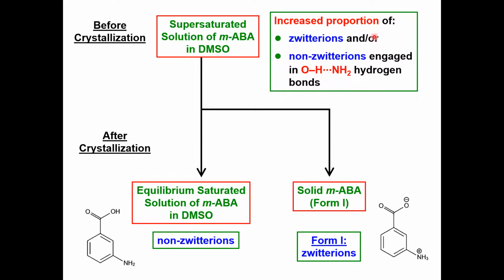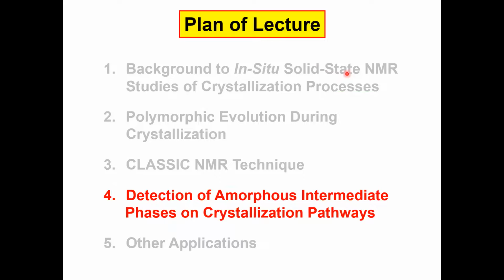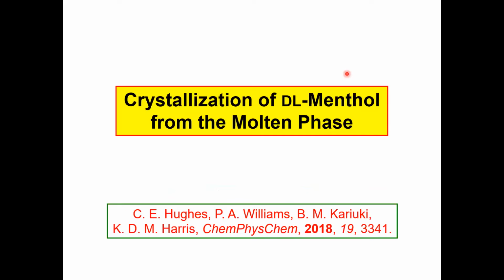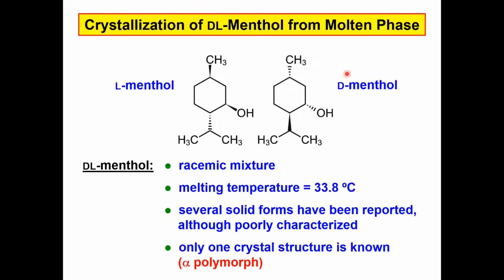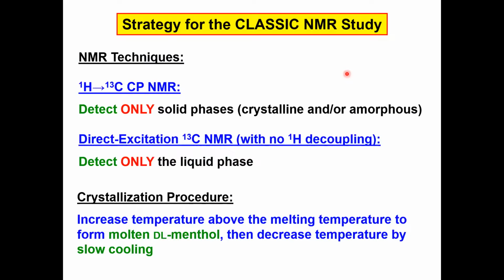And both of these scenarios described here are very plausible in terms of the type of precursor that may exist prior to crystallization in the supersaturated solution. So I want to move on quickly to the final two sections. First of all, detection of amorphous intermediate phases on crystallization pathways, for which there's quite a lot of interest at the moment. Now, let's look at crystallization of DL-menthol from the molten phase. So basically, we melt the DL-menthol and allow it to crystallize by cooling.